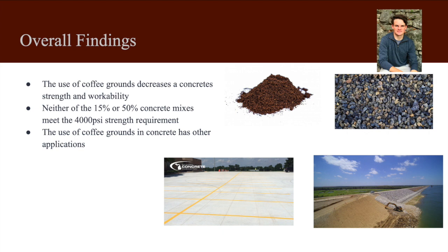We found that replacing 15% and 50% of our fine aggregate sand with coffee grounds is not realistic for parking lot concrete. This is because both mixes that used the 15% and 50% coffee grounds did not meet the minimum strength requirements for concrete used in parking lots or driveways, which is 4,000 PSI. Actually, both of these mixes failed before they even came close to reaching 4,000 PSI.